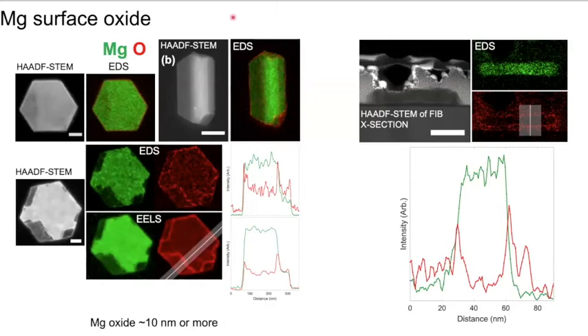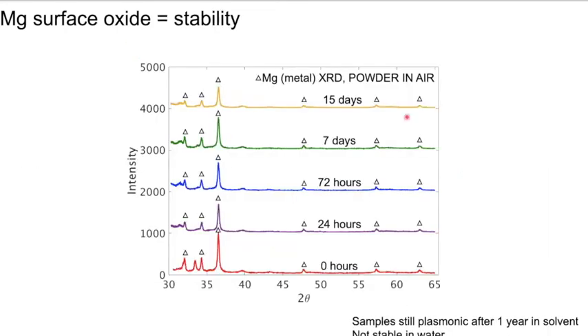So these are energy dispersive X-ray spectroscopy maps, for instance, of various types of particles. So this is a tent here, and then we have the hexagonal plates. We've even cut a little slice of these hexagons here, and then we're looking at this perpendicular in order to map the oxide layer around here. And all of our measurements are really quite heterogeneous, but the oxide is about 10 nanometers, sometimes more, sometimes a bit less. But the particles are never fully oxidized, so they remain plasmonic.